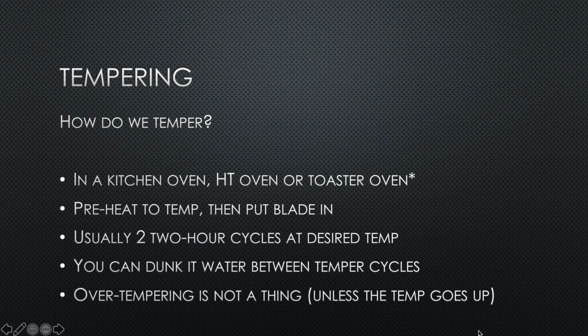So how do we do it? In a kitchen oven or a heat treating oven are both excellent ways, typically. You can use a toaster oven, but you need to be careful because sometimes these things have a wild range in their temperatures. Even though you set it at 375, it could go from 325 up to 425. So you need to be careful with toaster ovens.